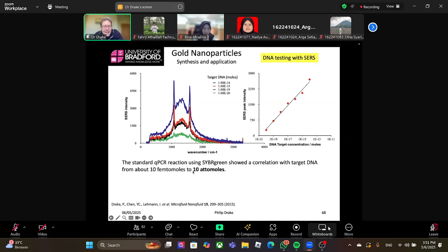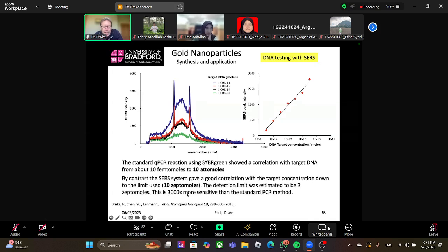Using this method, we can detect down to 10 zeptomoles. That's about 3,000 times more sensitive than PCR. So current standard art is PCR methods. This is about 3,000 times more sensitive because of the SERS from the gold particles.